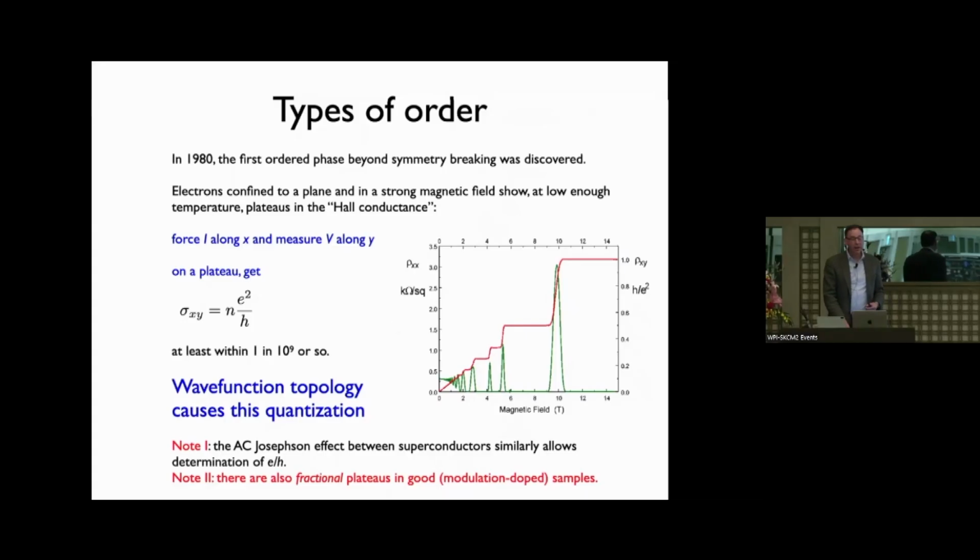And how this is going to connect to optics is the following. So in general, symmetry tells you whether a response is allowed in a material. And if it's allowed, it should be there. That's kind of a principle maybe due to Landau. The examples that are relevant to optics, maybe the most relevant ones: if I break inversion in a material, that will allow second harmonic generation, meaning light could come in at omega, and I will measure light coming out at 2 omega, twice the frequency.